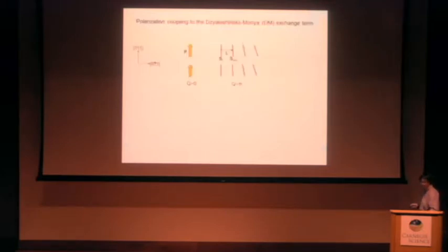And the details of that mapping, I'm just going to go briefly through this, not really trying to get an exact model, but this probably will help you understand how we think about this. So here, basically, that's a spin structure in BFO. Along the one-one-zero direction, you have spins being antiphase. Along the perpendicular cycloid direction, the zero-one-bar-one direction, the spins sort of rotate from the cycloid plane.